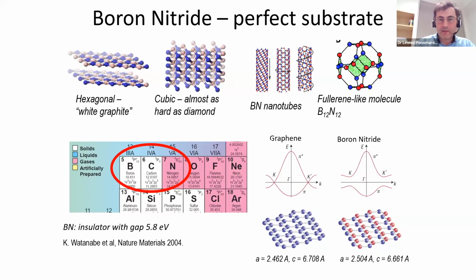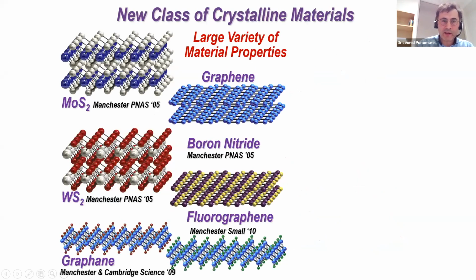It's atomically flat. The reason why graphene on silicon oxide is not so good is because silicon oxide is rough on a nanometer scale, but boron nitride is absolutely flat. So when we put graphene on boron nitride, electrons can travel many millions of interatomic distances without being scattered. That actually makes them so mobile. So the mobility is that high.